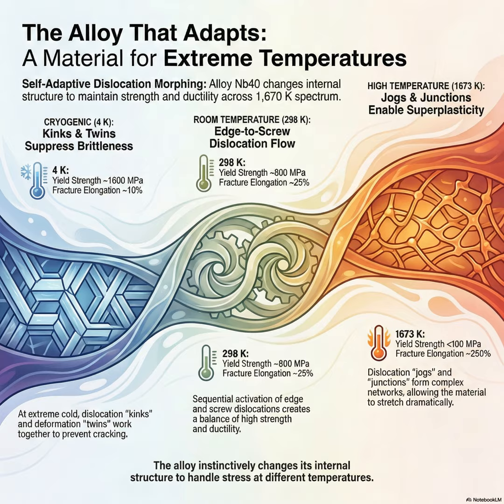Exactly. Okay, final turn of the dial. Extreme heat. Mode 3. The jog junction strategy that leads to that crazy superplasticity. Right. So at 1673 Kelvin and above, thermal energy is everywhere. Dislocation mobility is hugely enhanced, and as they move, they start forming these little deviations from their path called jogs. Jogs, little hiccups in the structure.